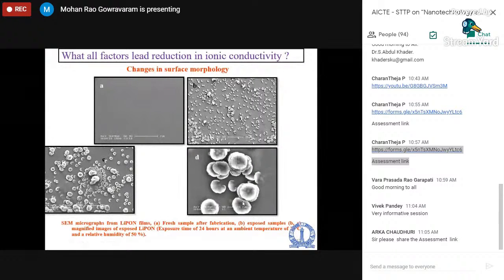Now, one of the reasons for this kind of eruption in thin films is what is called stress in thin films. When there is an eruption, then we say that there is a stress in the film. The stress comes because of the thermal expansion coefficient mismatch, lattice mismatch, and all that. So ideally, we thought that this may be the reason. Then what we did was to deposit this LiPON film on silicon, but with an intermediate layer of titanium.